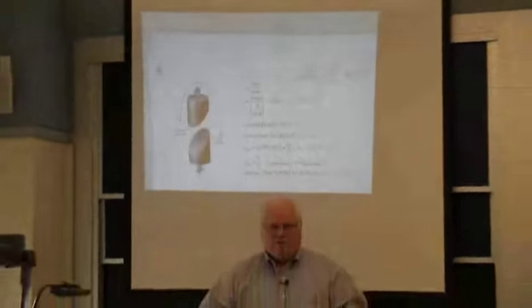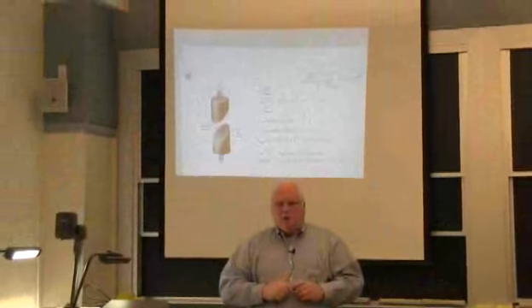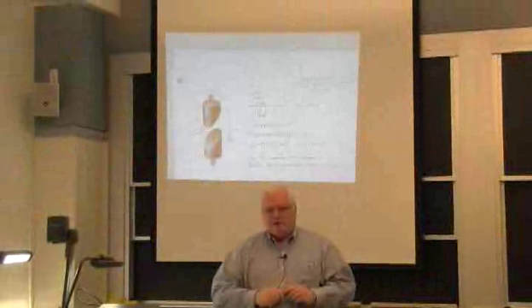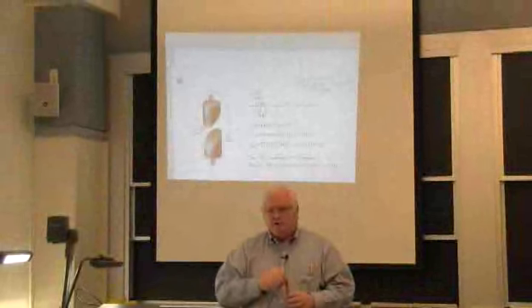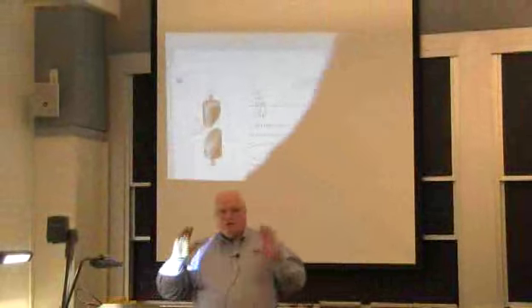So if I do a simple tensile bar and pull on this thing and measure a force per unit area to break it, just like we did with that piece of copper, in fact, the shear stress is half of that value. It's actually failing in shear on some plane, ideally at 45 degrees, but the shear stress will be half of the tensile stress. Okay? So the tensile stress is one of those normal stresses.